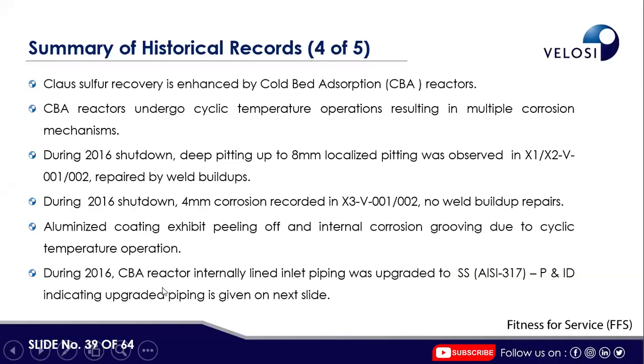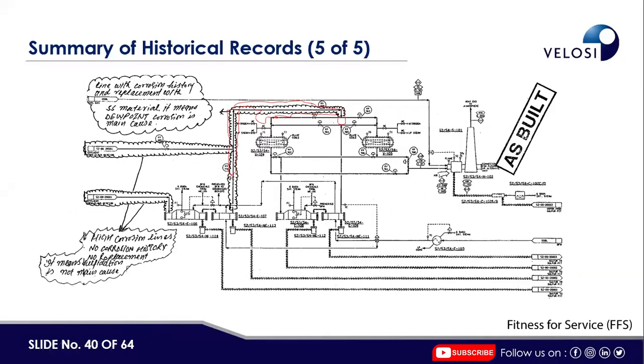During 2016, the CBA reactor internally lined inlet piping was upgraded to SS 317. The PFD indicating the upgraded piping is given on the next slide. So this was one of the lessons learned for the FFS team as well. If this lined part of the piping was changed, it means there was some issue with the carbon steel, which was not aluminized. Due to this reason, these vessels were facing this problem, and as a result of this FFS, a similar kind of upgrade was also suggested as one of the recommendations.